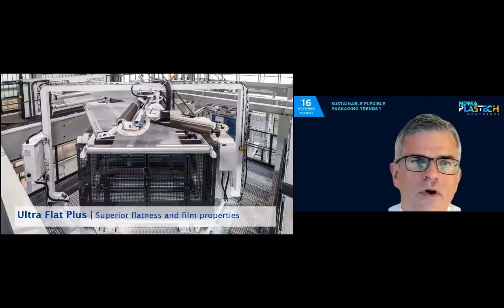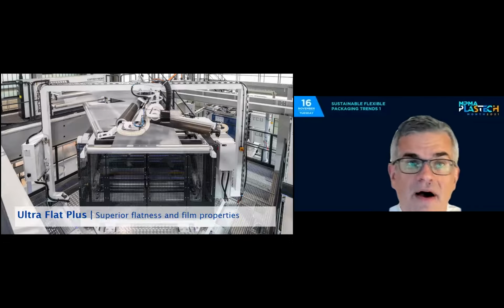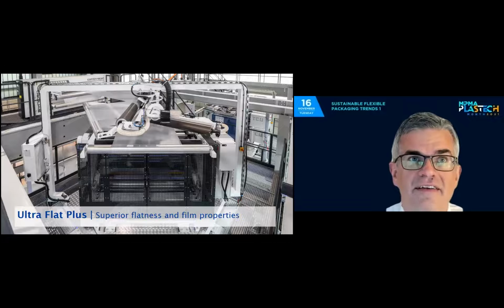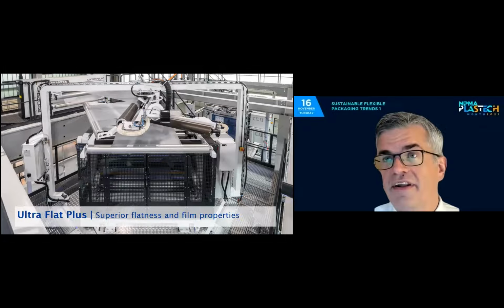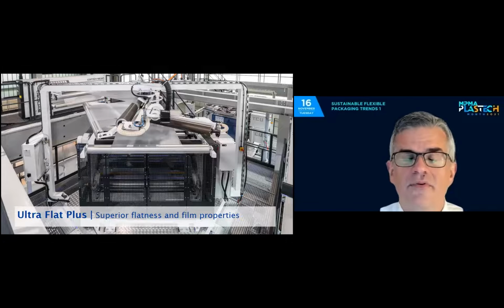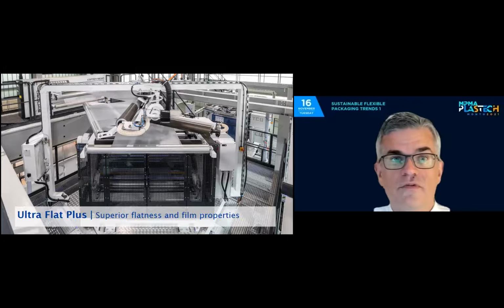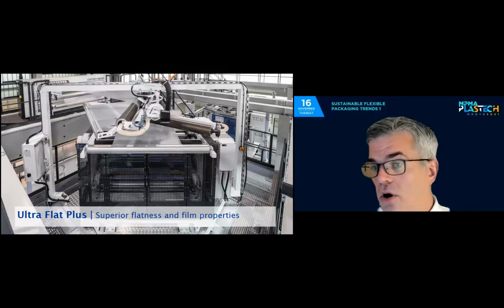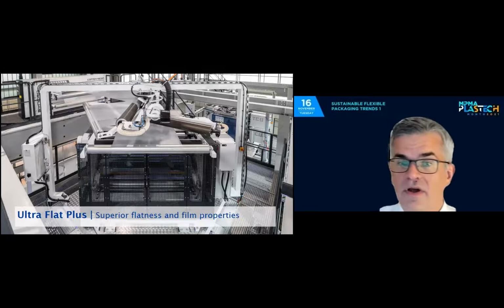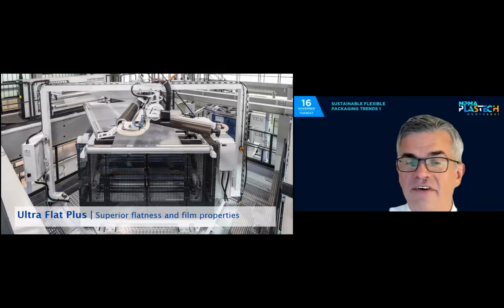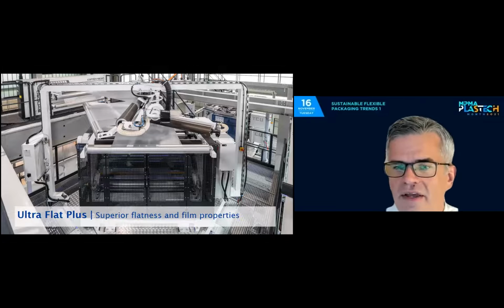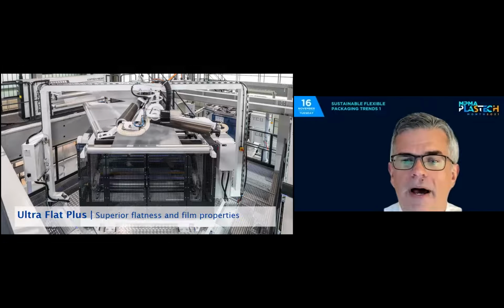So what can we do about that? Well, in my previous presentation, we saw the solution of using PE as a material and creating properties by stretching 300, 400, even 500, 600% to change properties, so these PE films become a possible solution for the substitution of PET film or bio-PP film. And if we talk about stretching, one can stretch a little bit lower. This is the way to modify the properties of those biopolymers.